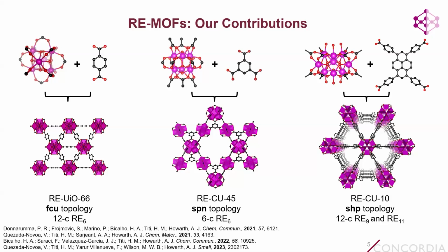And in all cases, we can confirm that our cluster nodes do have a mixture of bridging hydroxo and bridging fluoro ligands in them, although the exact ratio of ligands to each other depends on the exact metal organic framework and a little bit on the conditions that we use.